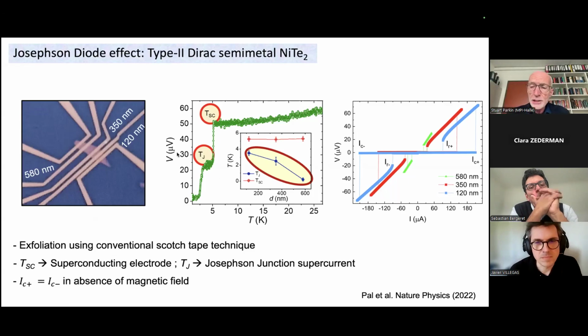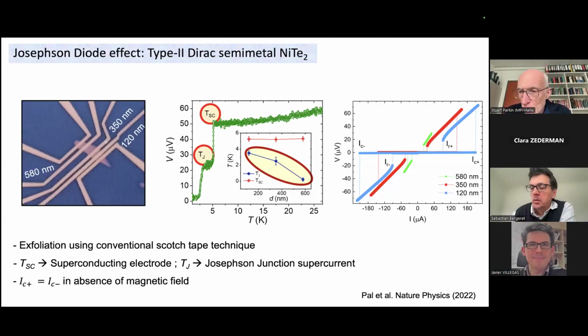So on the right-hand side, you can see a plot of the voltage between two electrodes as a function of the current. And you can see at small currents, the voltage is zero. As the current is increased, let's say take the blue curve, eventually the system becomes normal and the voltage will go from zero to a finite value. And there is some hysteresis because of the capacitance of these junctions.